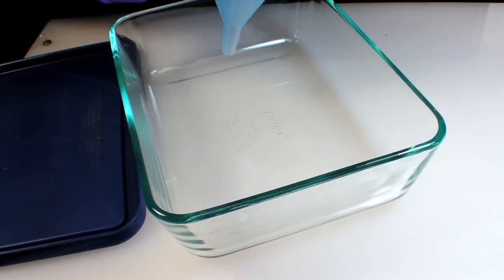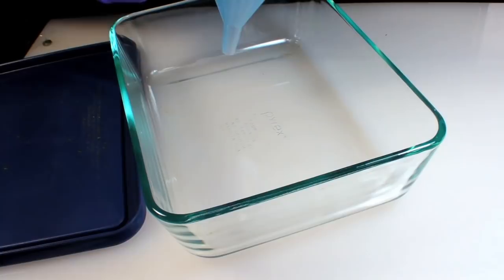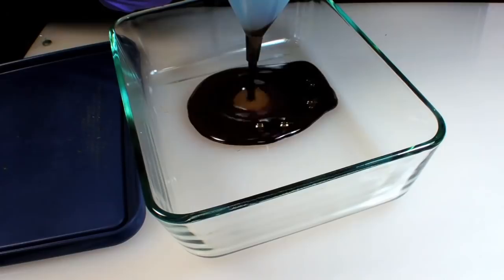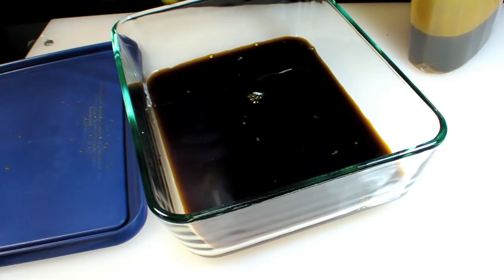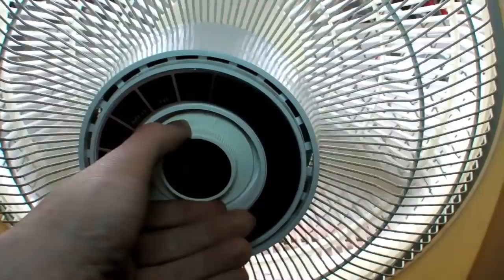There's a number of chemicals you can use for etching, but the most popular is probably ferric chloride. I'm using a mixture of one part concentrated ferric chloride to one part water. Now be careful as this stuff will stain almost anything and easily mess up any metal surface. You'll definitely want to avoid skin contact and keep a well-ventilated work area.